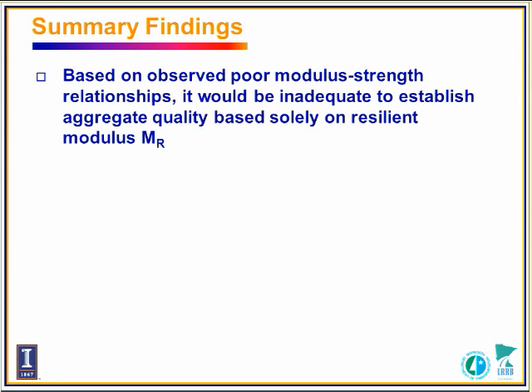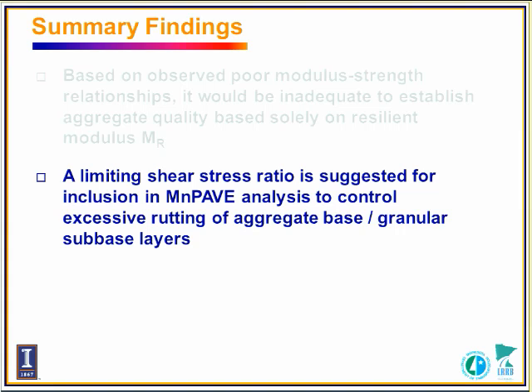Based on the previous figure, you can see that the modulus strength doesn't always have a unique increasing or decreasing trend. So we found that it may be inadequate to establish aggregate quality based just on the resilient modulus. Especially in the MEPDG guide, they recently focus on the resilient modulus side, but regarding rutting behavior and shear strength, I think we need more inputs to quantify those behaviors. To avoid rutting failure, we came up with a limiting shear stress ratio and suggest its use in the future.